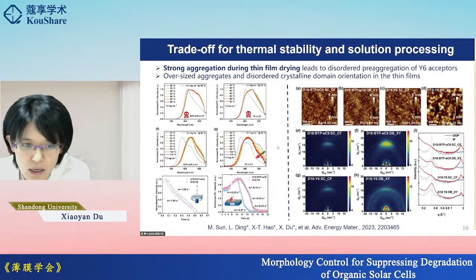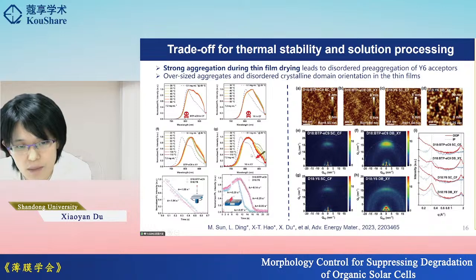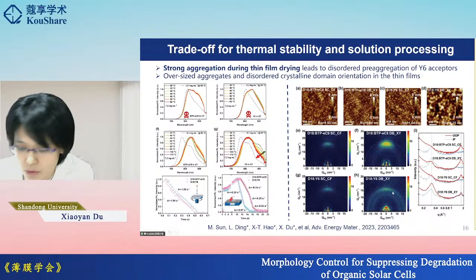The reason for this performance loss for materials with shorter alkyl chains is that in halogen-free solvents, the solubility is worse, and the materials easily aggregate in solution. This pre-aggregation in solution leads to the kind of morphology observed from AFM, with disordered crystal orientation. All of these morphological features are detrimental to the device performance.